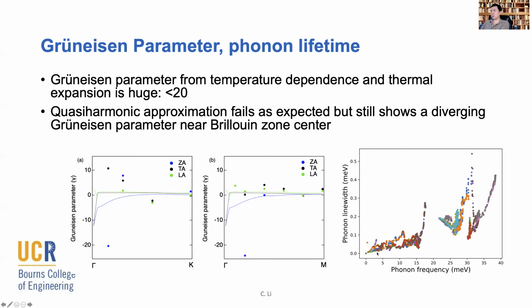And our phonon lifetime calculation clearly also indicates that, well, this is plotted for different branches, so you can see different colors, but it's hard to see here. What you can tell, well, you have to believe what I'm telling you, is this particular Z mode actually has a very, very long lifetime. In return, you get a very narrow phonon linewidth in comparison with other acoustic phonons.